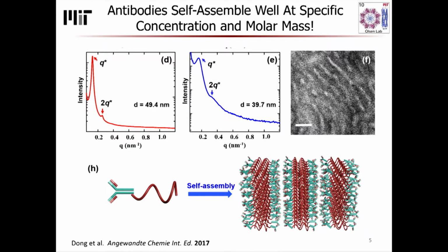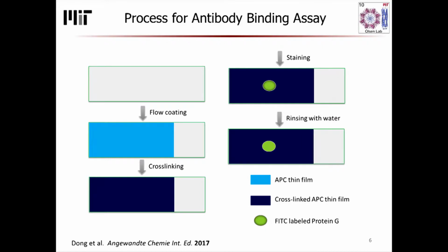What's really impressive beyond the ability to build three-dimensional nanostructures of these materials is that protein polymer conjugates or fusion proteins have a very high viscosity compared to protein solutions. And this allows you to incorporate it into industrial polymer processing equipment. It allows us to process sensing layers in ways that we would often think of processing polymer films. And so we actually just take simple glass substrates, silicon substrates, or even fabrics, and we can flow coat or dip coat the block polymer coatings right onto this surface. We lightly cross-link it in glutaraldehyde for about 30 seconds to immobilize it. And then we're left with a sensor that, when introduced in contact with some sort of functional moiety, can produce a sensing response.